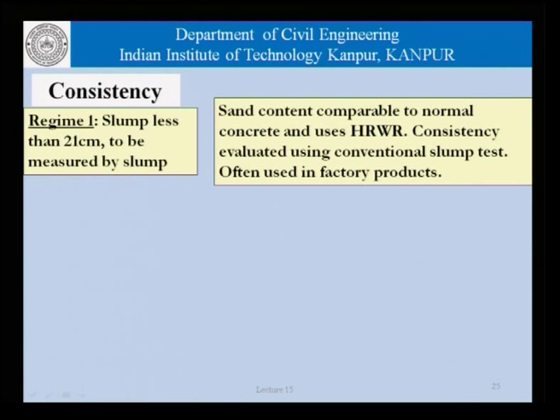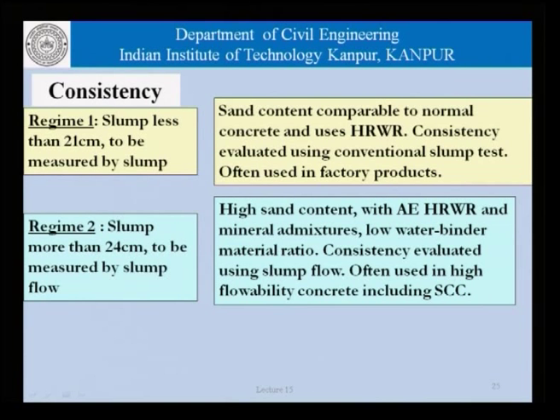At this level, the sand content in the concrete is comparable to normal concrete, and of course, that concrete has high range water reducers, and the consistency can be evaluated using the conventional slump test, and that is what is used in factory products. Whereas, if the slump becomes more than 24 centimeters or 240 mm, then we cannot really use slump as a measure for the consistency or the workability of the concrete, and we get involved with the slump flow regime.